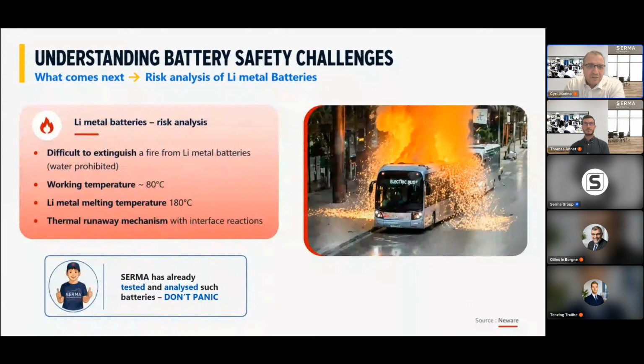So it means that to control it is not easy, because when you want to cool down this kind of system, you cannot use water, because water can react with lithium metal, and you will produce hydrogen that could create a very huge reaction in comparison to what you see in this picture here. So also at SERMA, we have already tested this kind of technology, so we can try to understand the mechanism, and we have seen that interface reactions are very important.